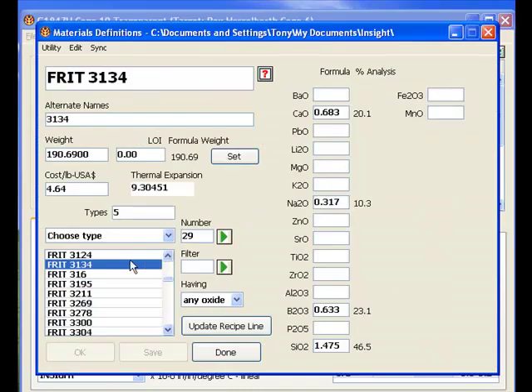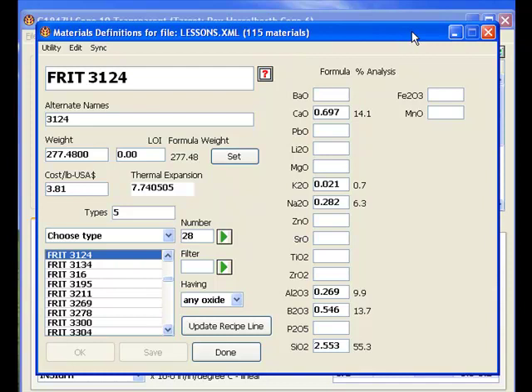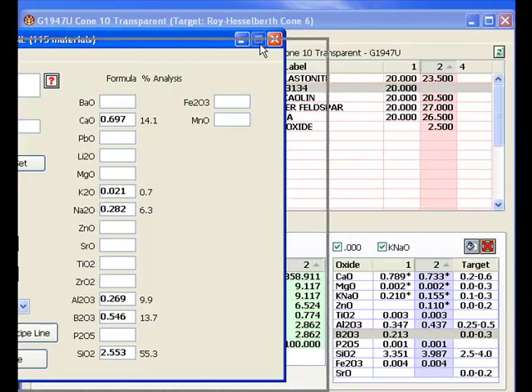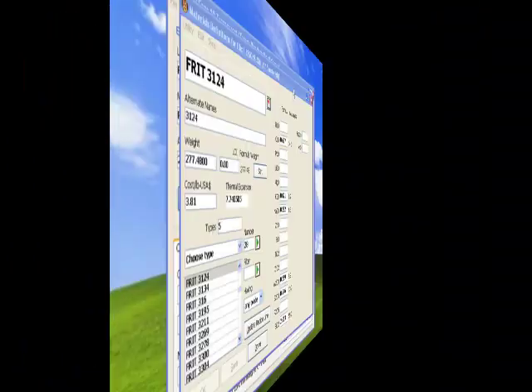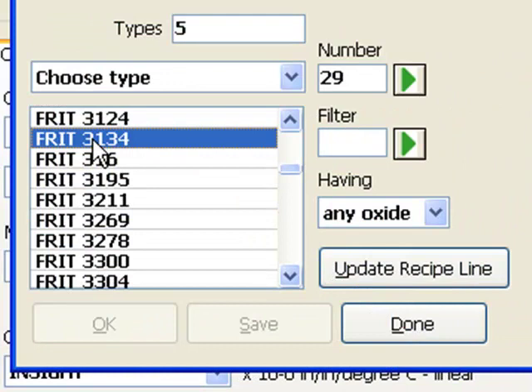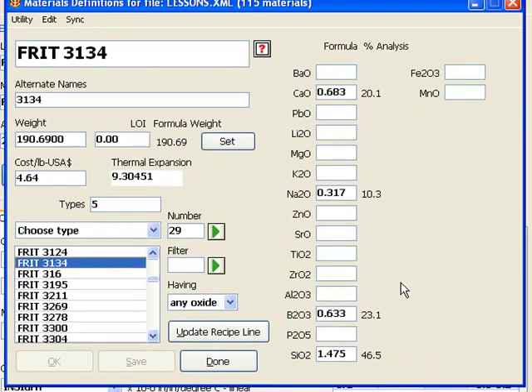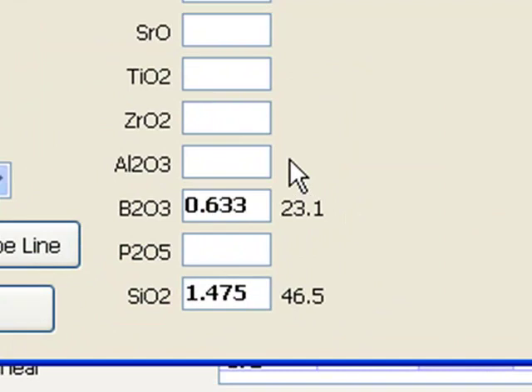But look at this typical frit. It sources so many other oxides besides boron. If we add this to a glaze, is it not going to throw the chemistry completely out of whack? That is why there are so many kinds of frits. Look at the oxides our Cone 10 glaze has — the frit does not contribute anything that is not already in the glaze. I'm going to use Frit 3134 instead. It has fewer oxides, so it's simpler, more boron, and it's the one already in the Cone 6 recipe I've opened. It also has no alumina, which will enable me to source Al2O3 from kaolin to suspend the glaze better.